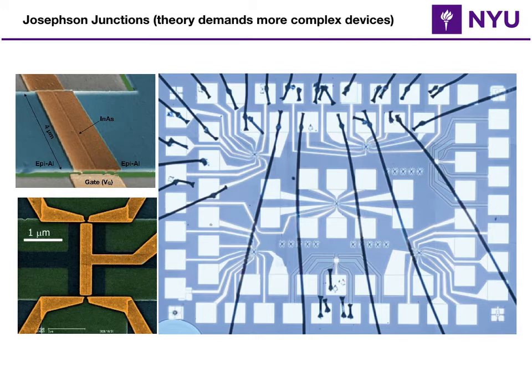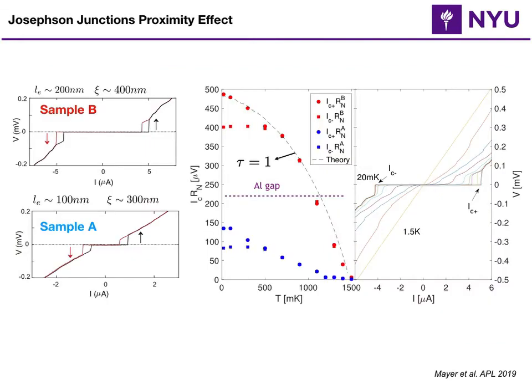The 2DEG, because it's a pseudomorphic growth, is quite challenging to get really good quality consistently. I mean, it varies and you can obviously pick the best ones. But here I want to show you an example of two samples, sample B and A. Sample B, the top left one, has a higher mean free path of 200 nanometers, while sample A has about 100 nanometers, right? If you make identical Josephson junctions, so the device geometry is the same, you can see that the supercurrent that sample B shows is about 5 microamps, while sample A shows only about a microamp of supercurrent. So everything is the same, just the quality of the 2DEG is different.